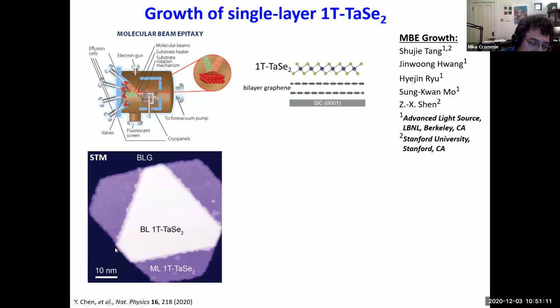So this is a big island. On the edges, you see the single layer, the monolayer 1T TaSe2, and in the center, the white part is the bilayer 1T TaSe2, and the dark blue is the bilayer graphene.